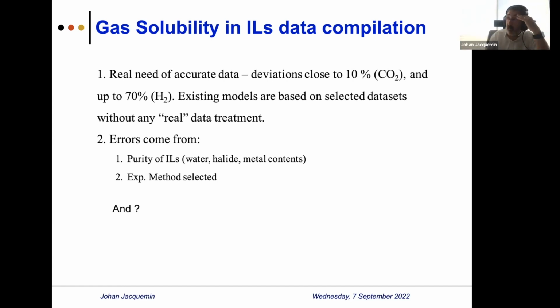In the case of ionic liquid, where could this problem come from? Probably purity of ionic liquid, stability of ionic liquid. We discussed during the previous talk about the purity of materials, and water is very sensitive, but we have also possibility of unreacted species, presence of halide, presence of metals, and this quantity must be defined in order to properly describe the ionic liquid. And we try, of course, as an editor of the journal, we try to force, I would say, authors to add information specifically for ionic liquid, but information are not always available.